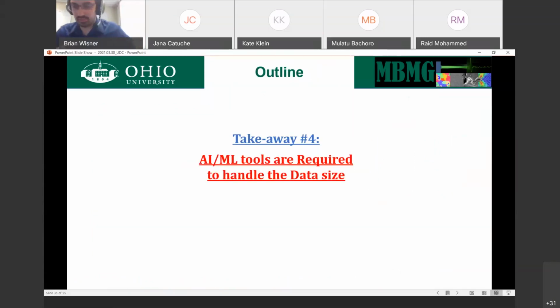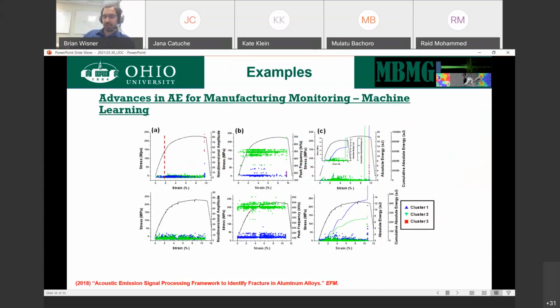That means we need some way of dealing with this in order to be able to make this useful for in-situ processes. If we want to be able to monitor the manufacturing process itself, we have to be able to do it in situ and process the data fast. That's where machine learning comes in. If we do all of this background work, we can start to piece together based on the microstructure, based on the NDE, based on various investigations we're doing, very controlled experiments and combinations with modeling. We can identify the difference between final fracture, damage initiation, and noise. From there, we now have the chance of saying, okay, if I'm doing a process, if I'm manufacturing this, I want to see if I induce a crack during my process. Well, now I know what a crack looks like.